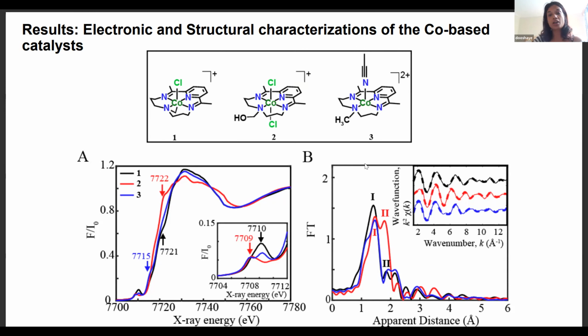So as we can see, the cobalt catalyst with the cobalt-nitrogen and the chloride ligands shows 2 peaks within the first coordination sphere, whereas the one with just 1 chloride ligand has a weak shoulder at much longer distances. Importantly, our experimental EXAFS agreed very well with the simulations and the calculated EXAFS profile from XRD and DFT optimization, showing that our methods and theoretical findings are correct and can be used for determination of the intermediate species along the catalytic cycle.